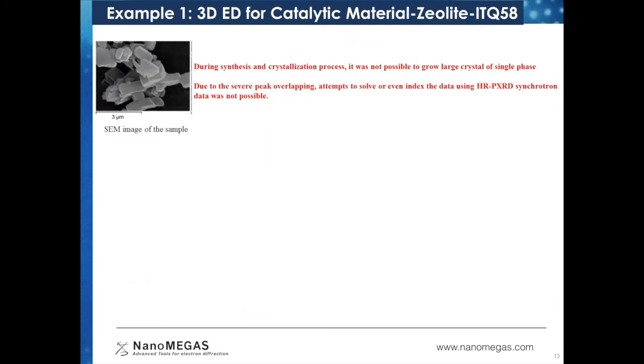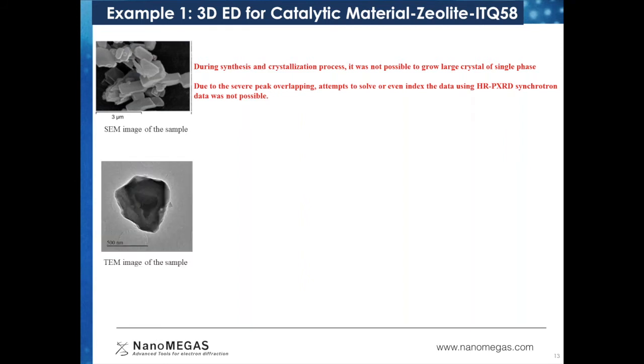Now, in the next 4 or 5 slides, I'll cover 4 examples selected from our work where 3D electron diffraction has been applied. The first one is a zeolite example where it was not possible to grow any large single crystal of single phase, which is suitable for single crystal X-ray diffraction. Neither was it possible to extract any structural information from the synchrotron powder diffraction data. In this case, we applied 3D electron diffraction methods.